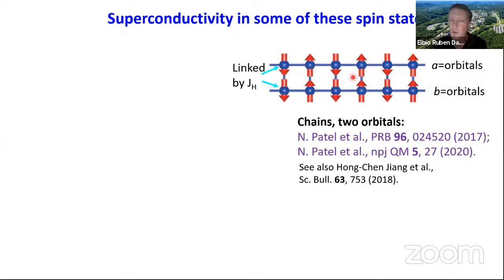This state, as shown in the cartoon, is incorrect. This state actually is far more exotic. It has exponentially decaying correlation functions. It has a spin gap, and it has exotic edge states, spin one half edge states. So what follows is an exploration of this, but from the fermionic point of view. Because rather than using explicitly spin ones, we can use the fermionic version. Now we have a Hubbard system with two orbitals, and that will allow us, among other things, to dope with holes. You can check these publications.